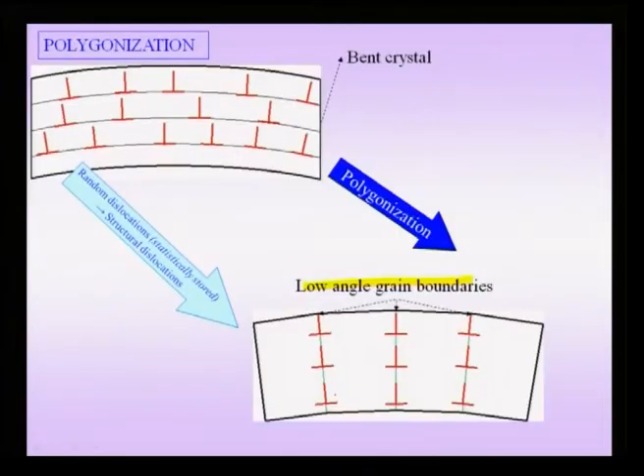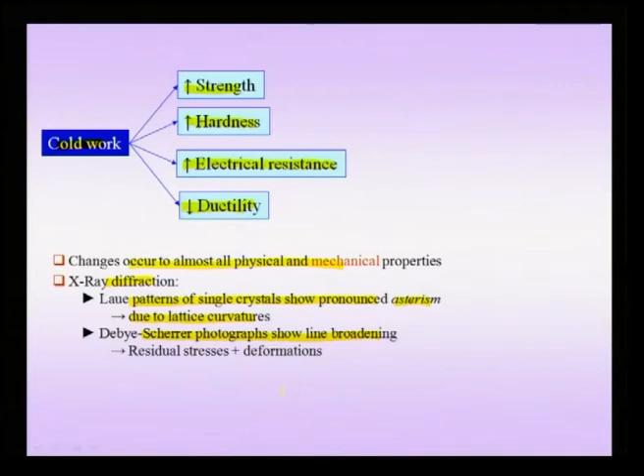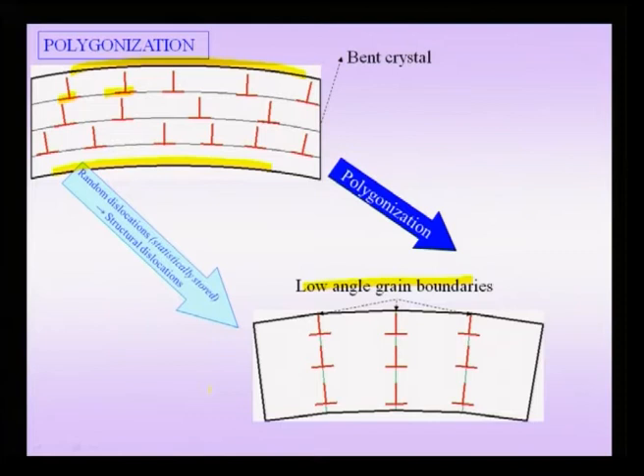present in a certain axis, then you can see that so many dislocations of the same sign actually bend the crystal. So, there is a pronounced bending of the crystal. Though this bending is small, the presence of many dislocations can give a certain amount of bending to the crystal, and this bending of the crystal, as we noted before, due to lattice curvatures, can lead to effects on the Laue patterns if you take Laue diffraction patterns.